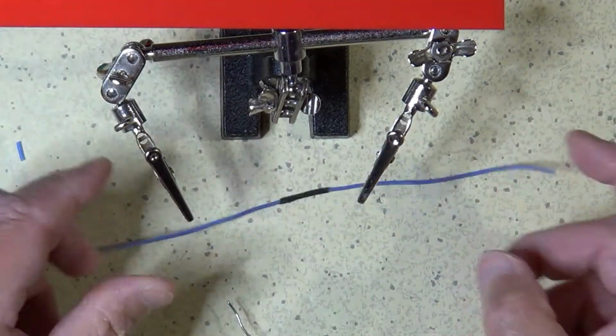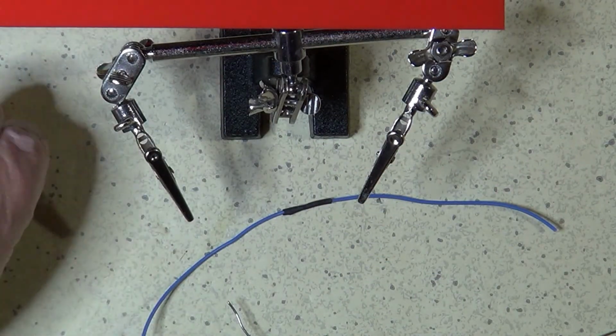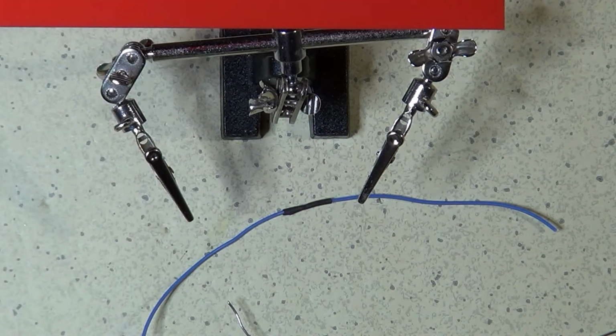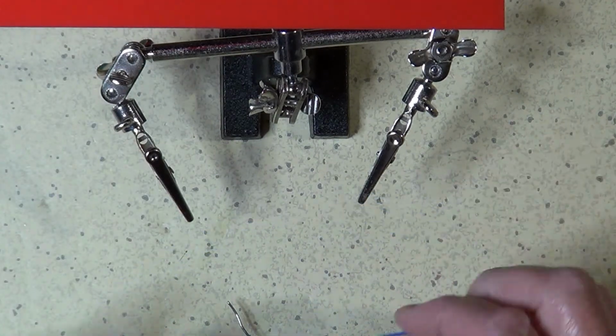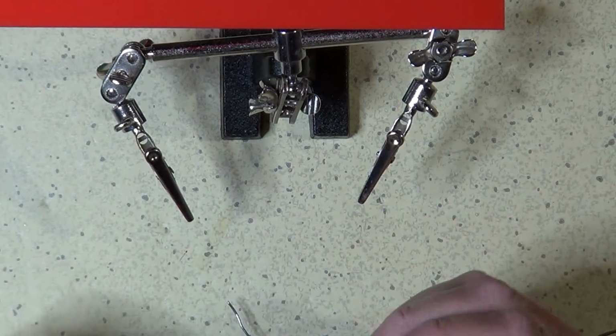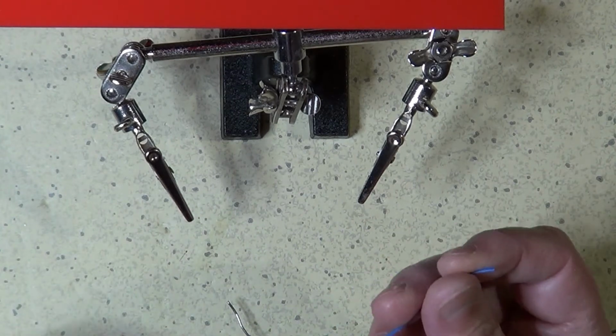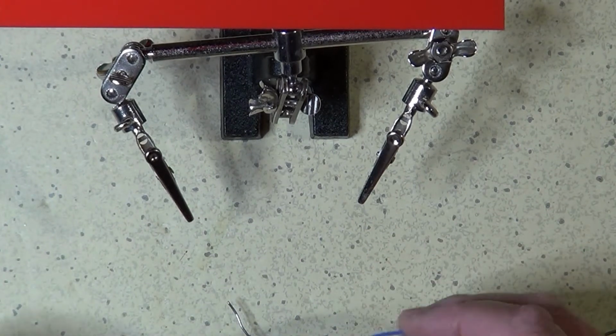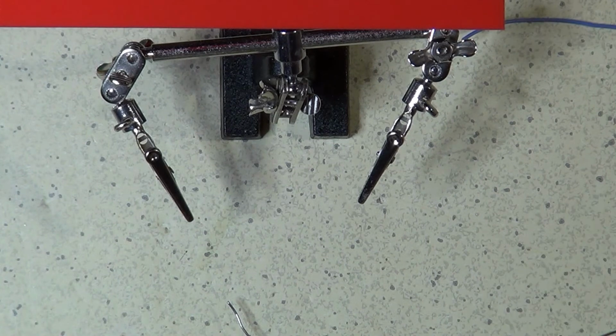Sometimes, especially if the wires were exposed for some time to the air, their surface could be covered with oxide. If that is the case, it is better to remove the oxide before soldering the two parts together, otherwise the solder might not bond with the wires and the connection could not work over time. This is especially true if there is a lot of oxidation on the wires, because the rosin core will not be enough to remove it.